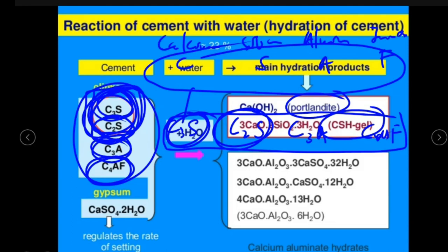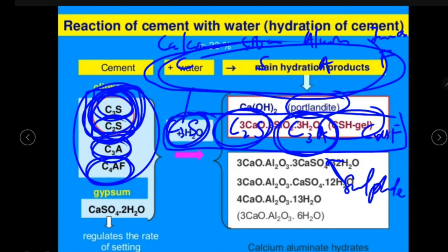What else of the cement can you think of? Sulfate resistant. So C3A is actually an undesirable compound in the concrete, but when we burn all four things together, it will appear. It is undesirable because when C3A meets sulfate, in general what we call sulfate attack, it will form calcium sulfoaluminate, that is ettringite, which is the thing that we don't want in the concrete. This is the root cause of sulfate attack. So if you want to produce sulfate resistant cement, we have to reduce this part instead of increasing it, so that there is less tendency for our concrete to be attacked by sulfate. That is how we produce sulfate resistant cement.